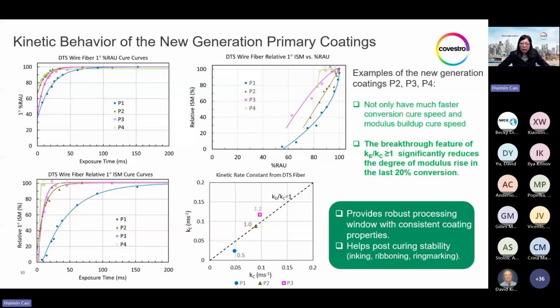Now, after seeing the theoretical curves, the question is whether a Ke over Kc ratio equal to 1 or higher than 1 can be achieved at all. This is the key slide showcasing our new generation coatings P2, P3, P4 versus the conventional coating P1. Not only are the conversion cure speed and modulus cure speed of these new generation coatings much faster, especially the modulus buildup rate, so much faster than P1, right?